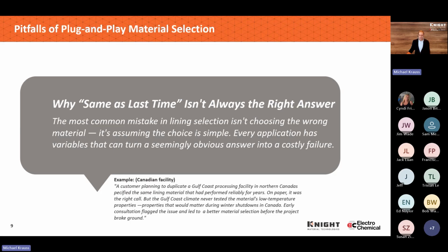The vessel itself was going to be an outdoor vessel, so if the plant was shut down for any length of time during the winter, they could see temperatures well below 0 degrees Celsius, probably approaching that in Fahrenheit as well. And PVDF is known to have embrittlement issues at low temperatures. So just because it worked and you're trying to make a duplicate, the situation was actually different.